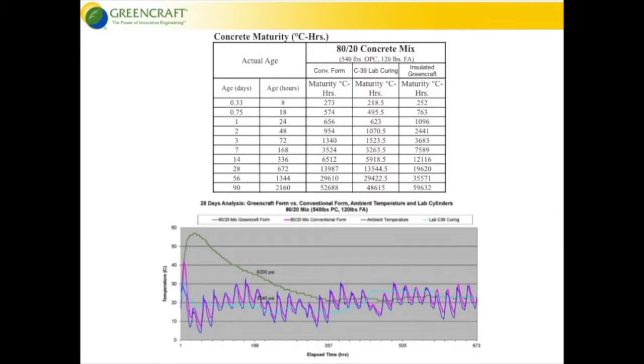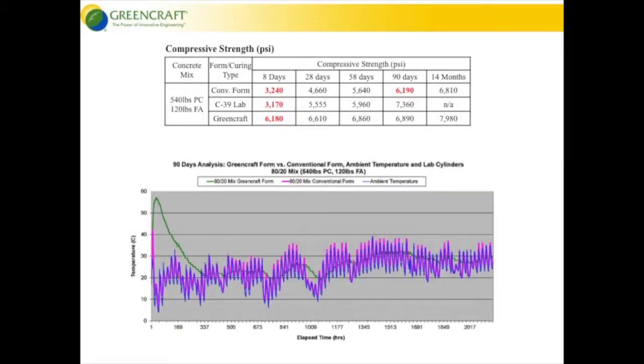So we cored a couple of samples out of each panel. The cores were done at 5 days. Then a weekend came and they didn't break them until the 8th day. So the insulated core was hot when it came out, but then it cooled off. So from day 5 through day 8, it didn't follow the same pattern as the concrete in the form itself. Yet, we have 6,100, 6,200 PSI, while the conventional form has 3,200 PSI. The lab cylinder has 3,100 PSI.